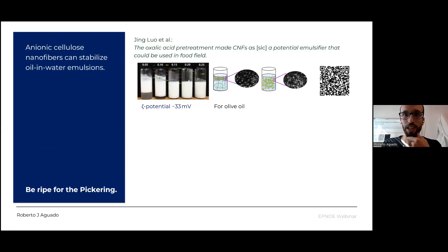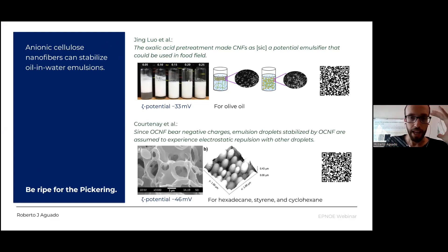I will also talk a little bit of physical chemistry, not so in-depth as Professor Capron said, but I will talk in terms of interfacial tension and giving out more questions than answers. Let's begin by a well-known fact. Anionic nanocellulose, even highly charged, work for oil and water emulsions. They are mostly prepared by TEMPO oxidation of cellulose, but carboxymethyl nanofibers or even esterification with diacids such as oxalic acid also lead to carboxylate groups.